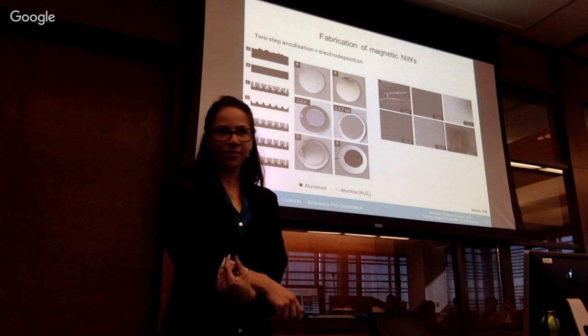And later, I just add a solution which contains metallic ions. I apply a pulse voltage, and that would attract the ions to the bottom of the pores, and I will fill up the pores with the magnetic material of interest. This is how a finalized successful sample looks like. Within this area, you have all your deposited nanowires, and you have a number around 10 to the power 9 nanowires within this area.